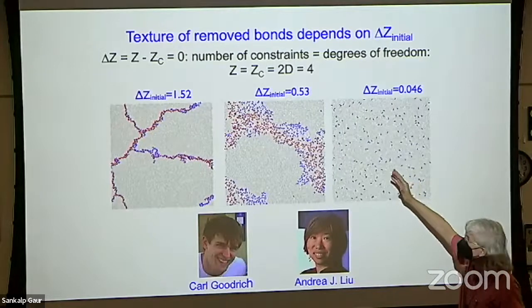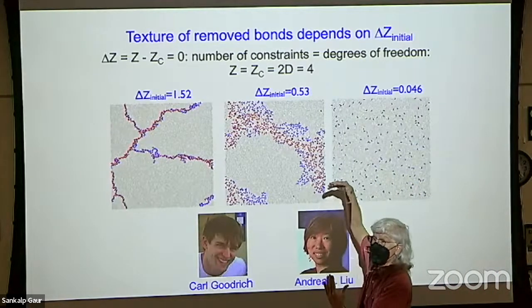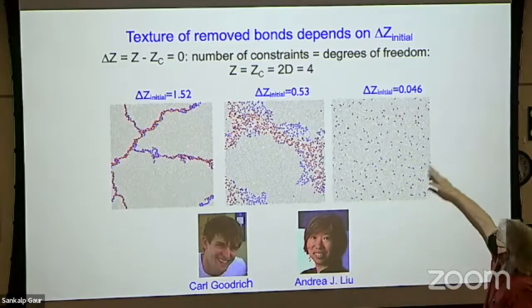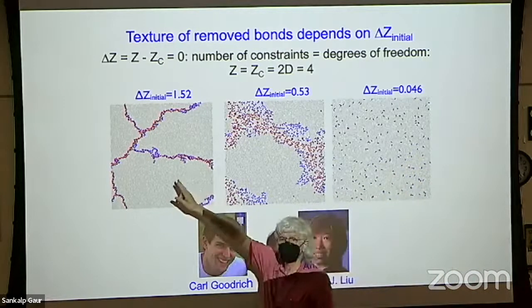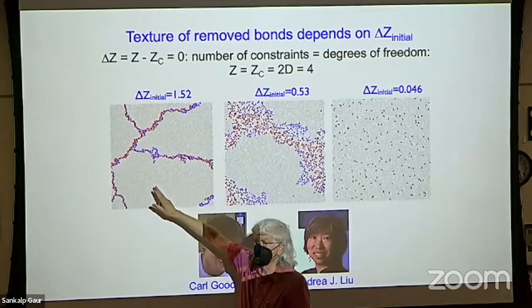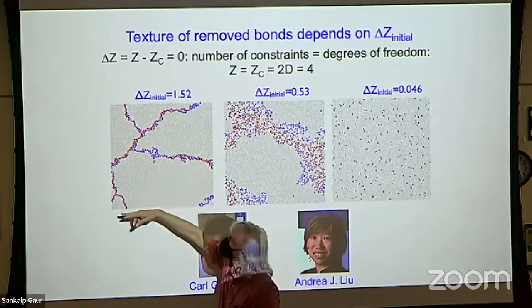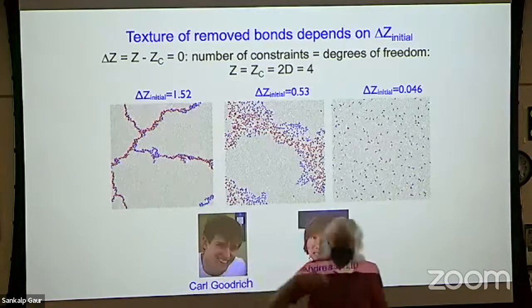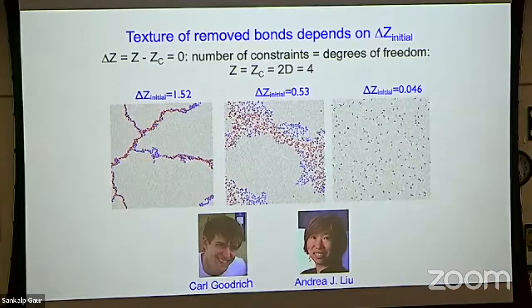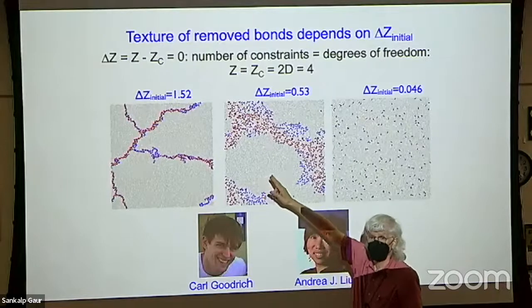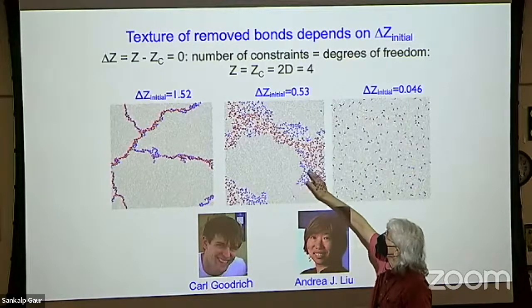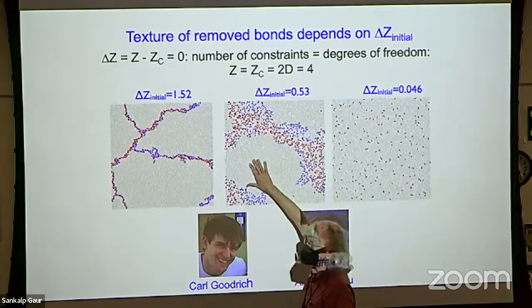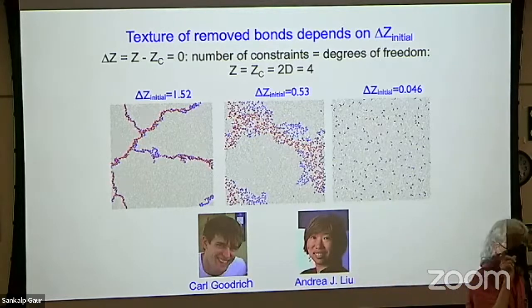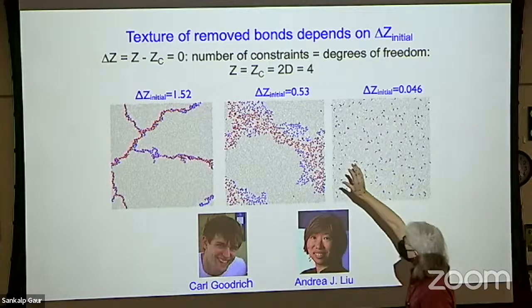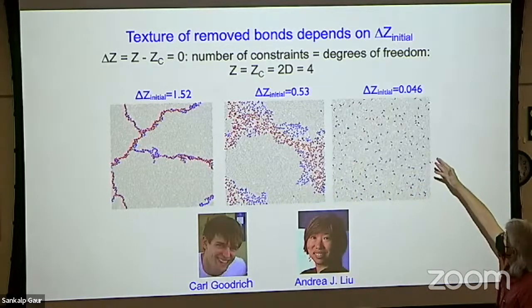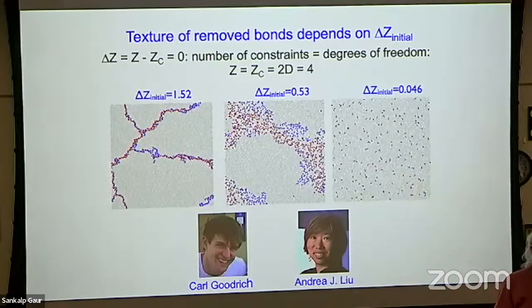So what these experiments did was take this two-dimensional system and squeeze it in both directions. And here we are, a regular solid, very far from the transition, very far from losing rigidity. You break these bonds and you get very classic behavior: cracks forming everywhere as you start squeezing this thing. But as you change the number of bonds that you start with, the cracks really are getting wider. There are big regions where nothing happens, but then you get these cracks that have a thickness, and you can measure the thickness of these failure regions. Then you get very close to the transition, and this failure zone is now the size of your sample.